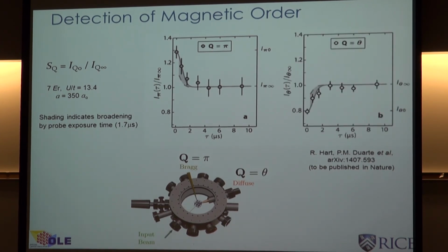Now, if we look at the other direction, this is the theta direction, this is the pi direction, we actually see a suppression. And what's going on there is that there are some doublons here, which this is sensitive to. If a site is doubly occupied, the scattered signals actually cancel, because the spin up state is emitting out of phase from the spin down. If they're in the same location, then they cancel each other out. And so if you have what are called doublons, sites where there are 2 atoms occupying it, that signal will go down, and that's what's going on here.